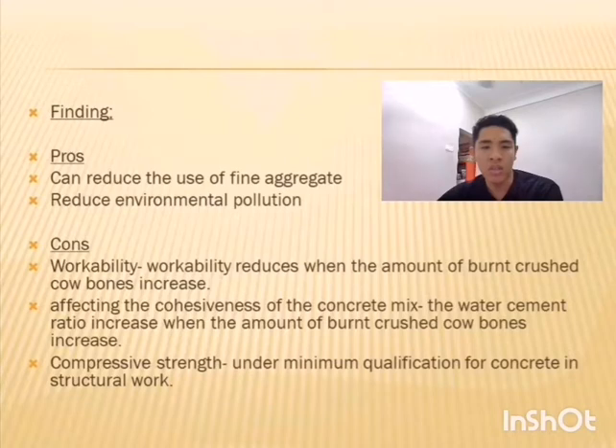The disadvantage is workability. The workability of the concrete will be reduced when the amount of burnt crushed cow bones increases. Next, the cohesiveness of the concrete mix will be affected. The water cement ratio increases when the amount of burnt crushed cow bones increases. Therefore, the slump will collapse. Next is compressive strength. The compressive strength of the concrete mixed with 40% and 50% burnt and crushed cow bones is under the minimum qualification for concrete in structural work.